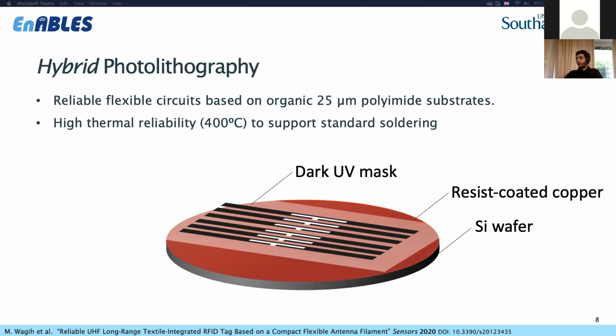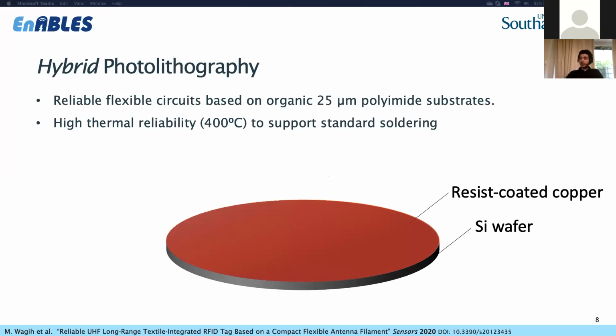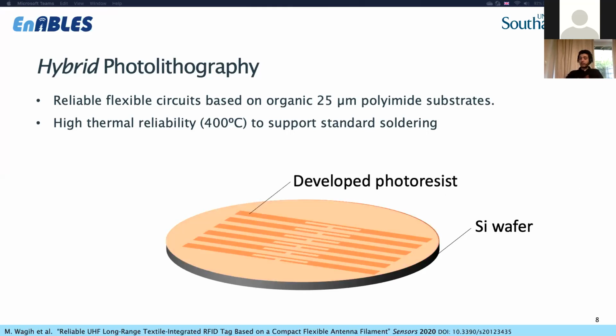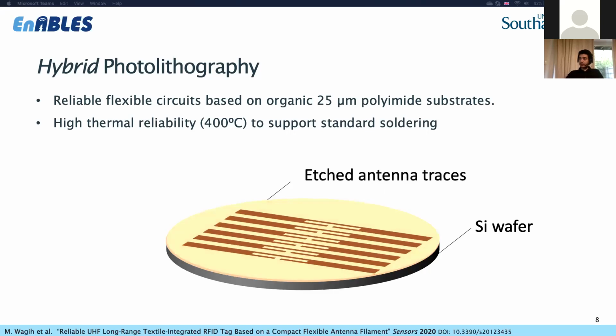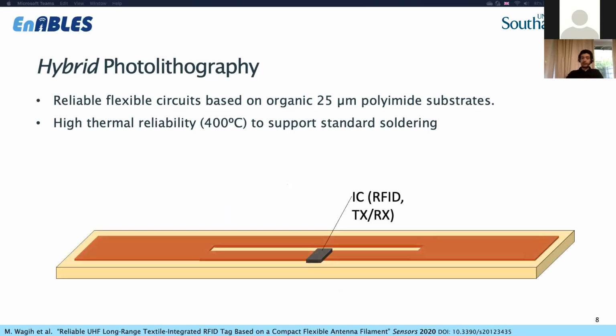Then we get a UV mask, which can be printed using any high resolution plotter, and we expose that to UV light, and we get the developed photoresist, which then has the patterns we have on our photo mask. Using a standard etching tank, which is commercially available and very low cost, we can get our traces, which can be PCBs, antennas, or complete systems. And once that is ready, we can then cut them, and we have our individual components, which we can mount on this board and then integrate in complete systems.